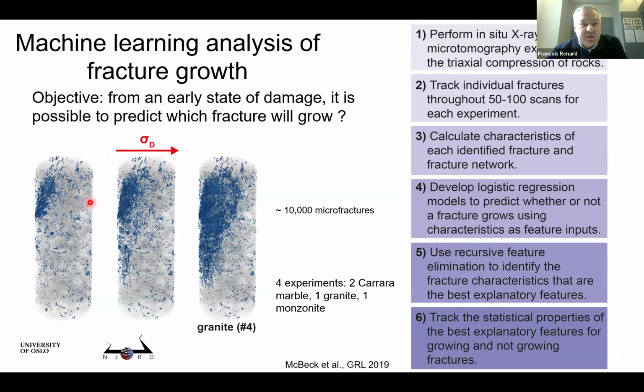We started with a series of experiments. We had 4 experiments, 2 on Carrara marble, 1 on granite, 1 on monzonite. We use these rocks because at the beginning, they don't have any porosity. So when we image the porosity as a function of time, it corresponds to the amount of damage that accumulates.